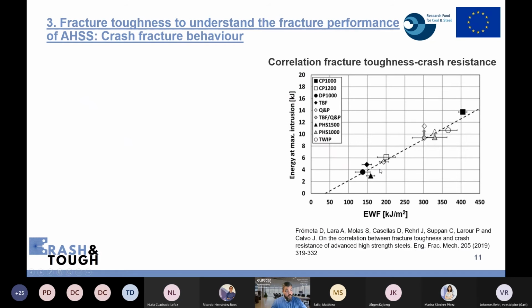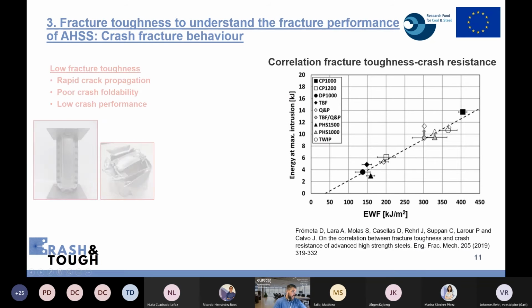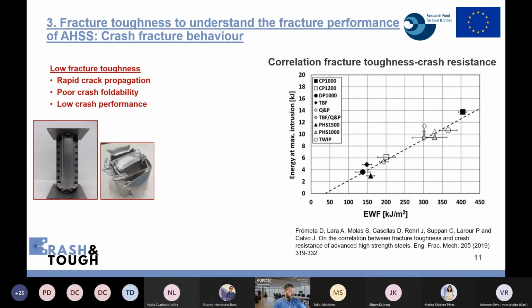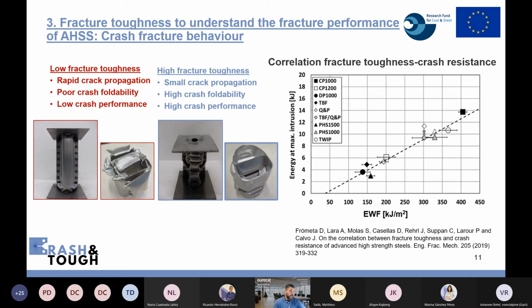Something similar occurred when we looked at the crash behavior in a previous project. The crash behavior in axial impact tests, also for several advanced high-strength steels, was quantified using a cracking index and also the energy absorbed at maximum intrusion. We observed that steels with higher fracture toughness in general showed better crash behavior. What we observed from the tests is that materials with low fracture toughness showed rapid crack propagation, poor crash foldability, and overall lower crash performance. On the other hand, steels with high fracture toughness show small crack propagation, high crash foldability, and a higher crash performance.